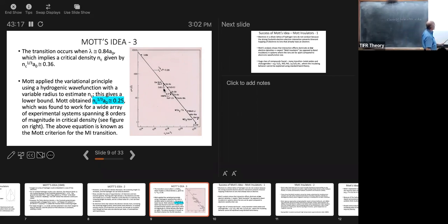Here is plotted the Bohr radius, and here is plotted the critical density, both on a log-log plot. This would say that you will get a straight line on this log-log plot, because it's 1/3 log NC plus log A naught is equal to a constant. And the slope is correct. In fact, the best fit to this data gives that constant 0.26.